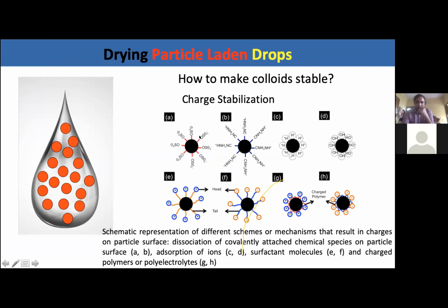group on the particle surface, and when particles with such a charge group are introduced into a fluid, these charges can dissociate, giving out either a negative charge or a positive charge on the particle surface. And positive or negative charges can also be imparted to the particle surface by dispersing them in different fluids where there's a specific adsorption of ions onto the particle surface.